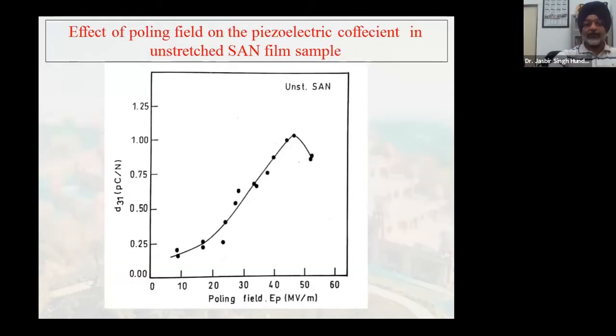Okay. Now this is the variation of the piezoelectric coefficient with the poling field. The best poling field was found to be 45 MV per meter for the film, right? Beyond that, if a higher field is applied, electric breakdown starts and the piezoelectric coefficient starts falling. So you get the maximum value of D31 when the poling field is around 45 MV per meter. Now with the increase in the poling field, we are increasing the polarization. And that is one essential feature of dipolar polarization, that polarization should increase linearly with the poling field. So this is almost the type of curve we have.